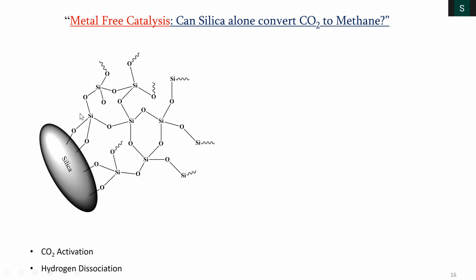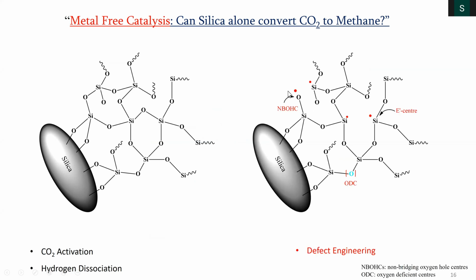How do I create the defect? See, this is the silica. I'm showing just the surface of the silica. This is amorphous: SiO, SiO, SiO, a random network of siloxanes. If I break these SiO bonds here, I will get O radicals and Si radicals. If I break both bonds, I will get 2 Si radicals, something like this. I get an O radical and a Si radical. This is called NBOHC, non-bridging oxygen hole center, because you broke the bridge. The Si radicals are called E centers. These are just names, but ideally it's Si radicals and O radicals. And if you break both the SiO bonds, then you get these oxygen vacancies shown here.